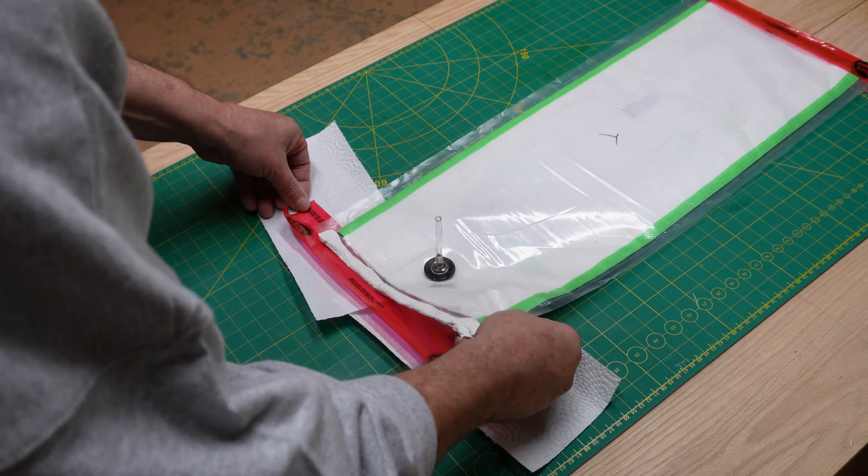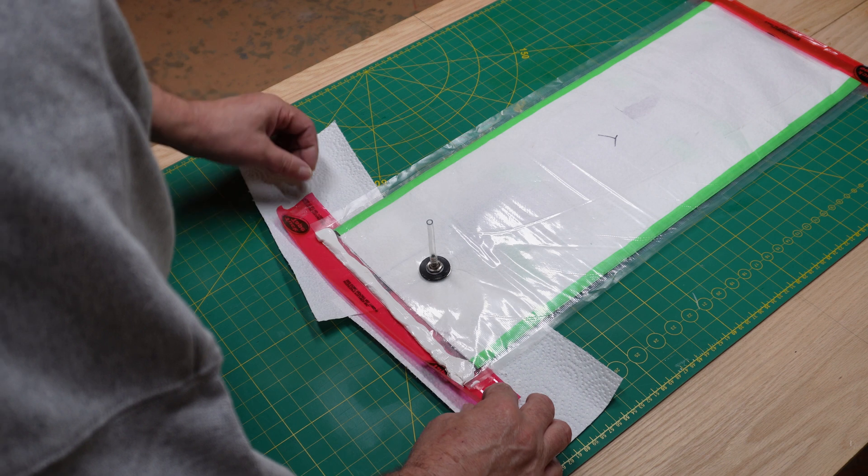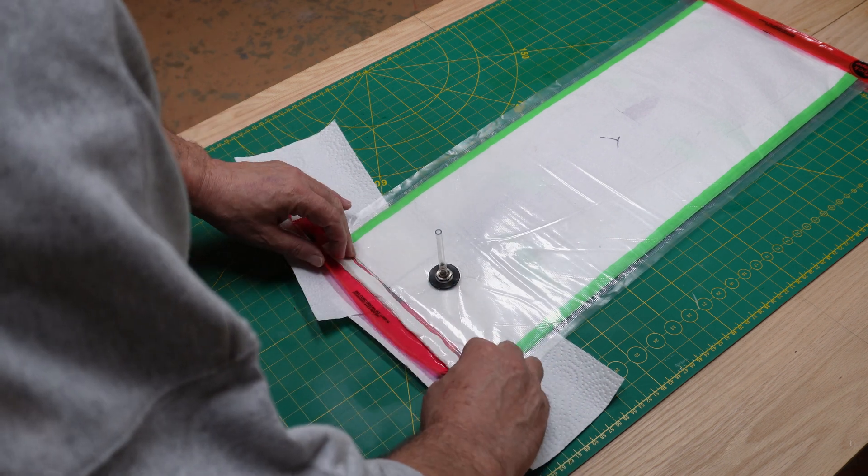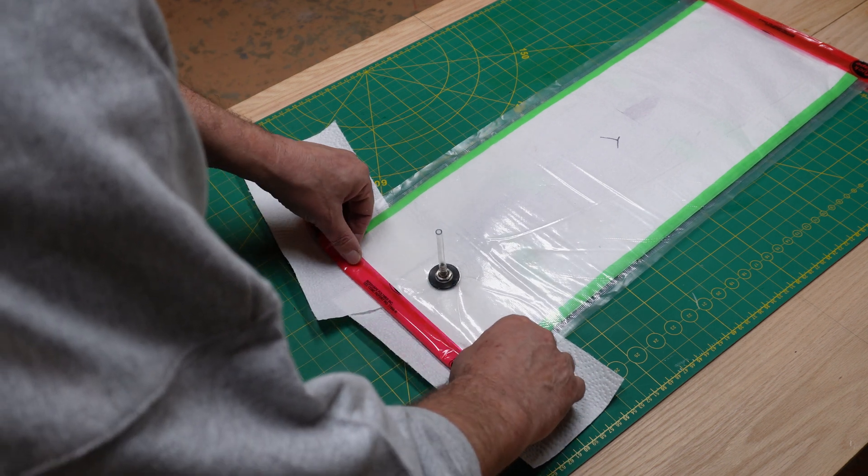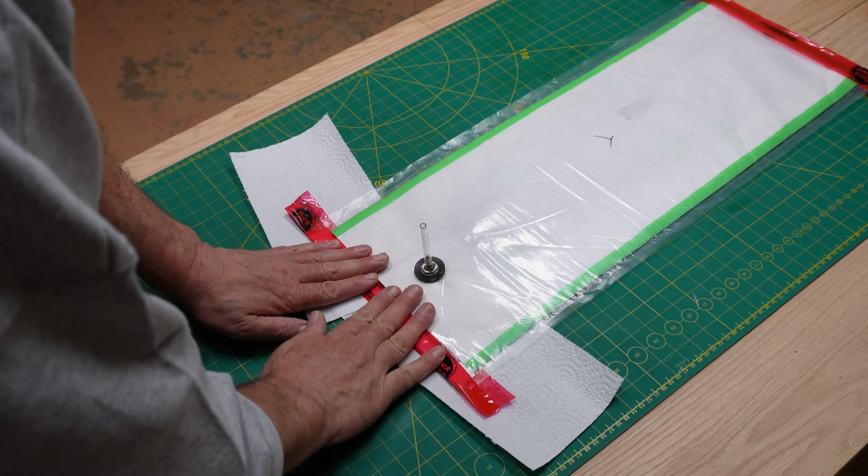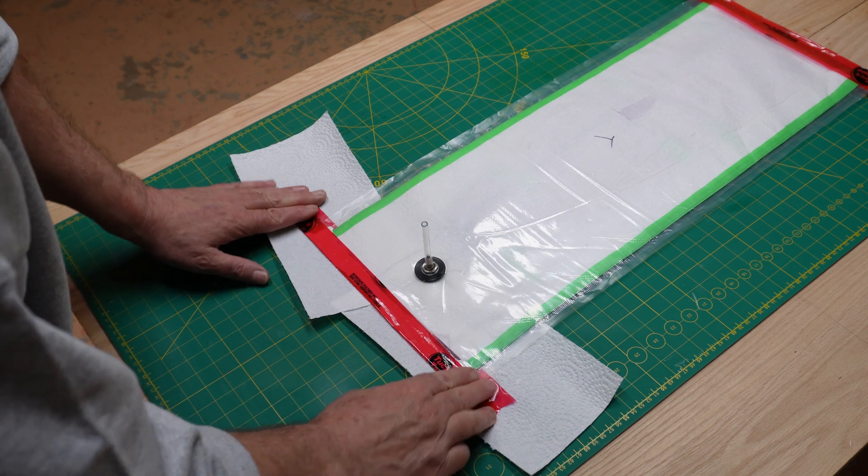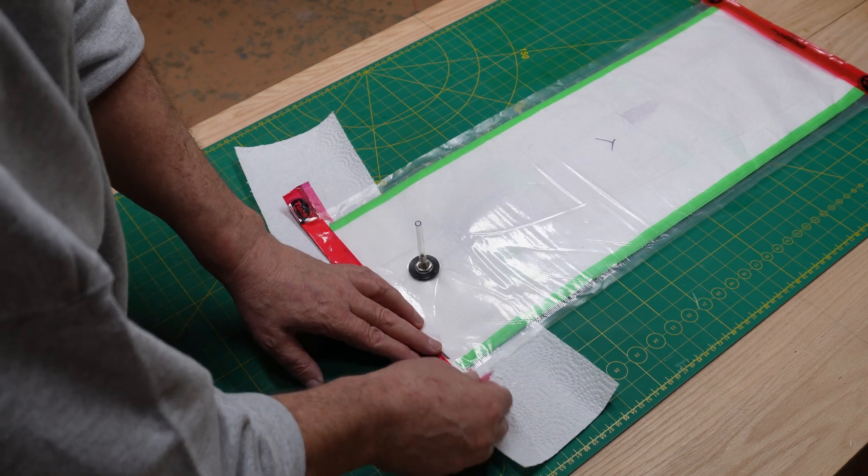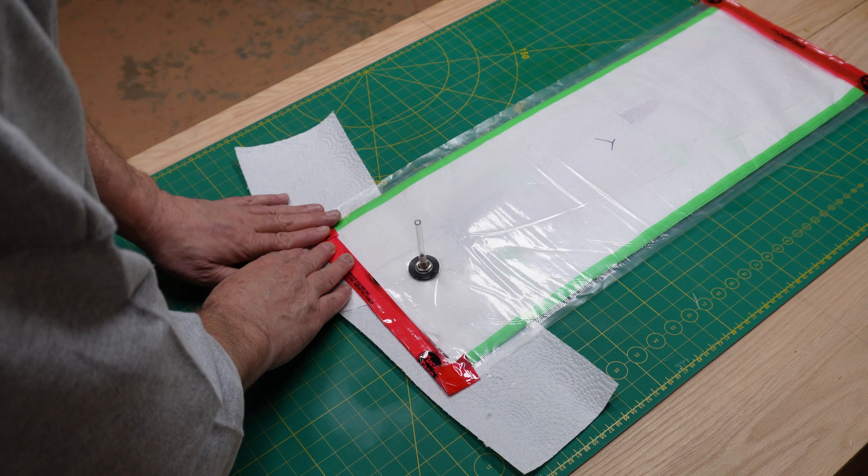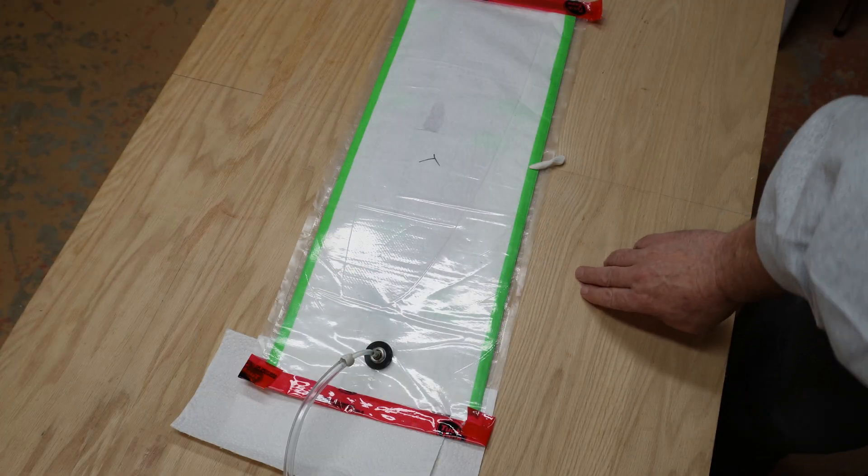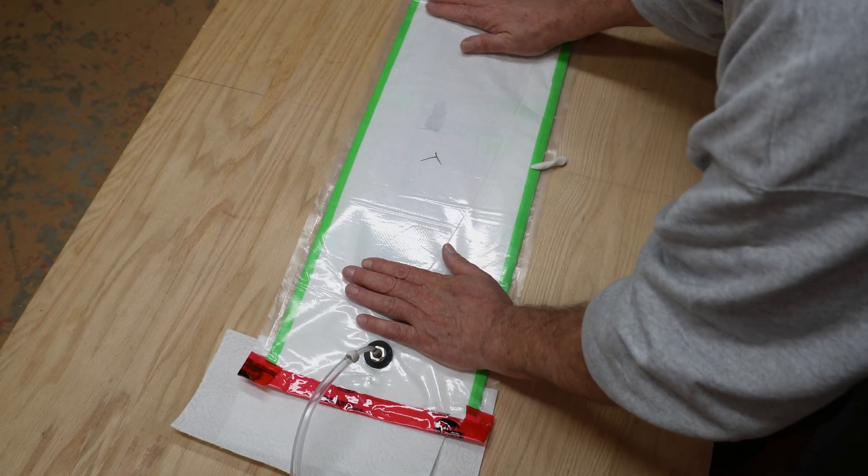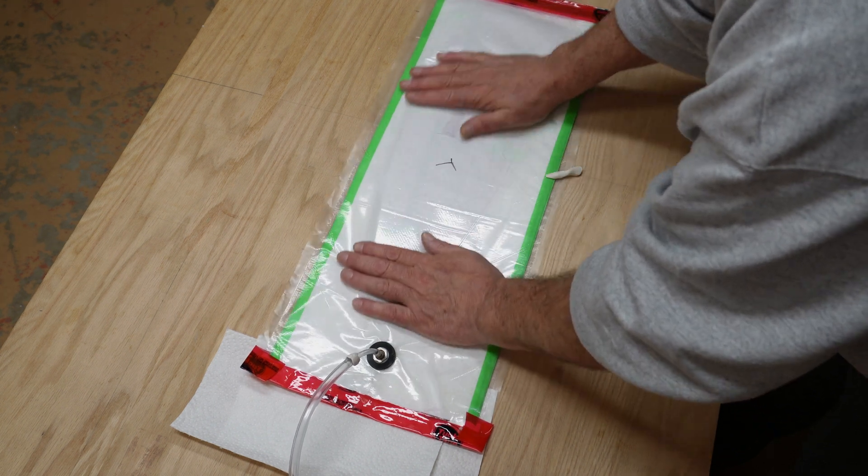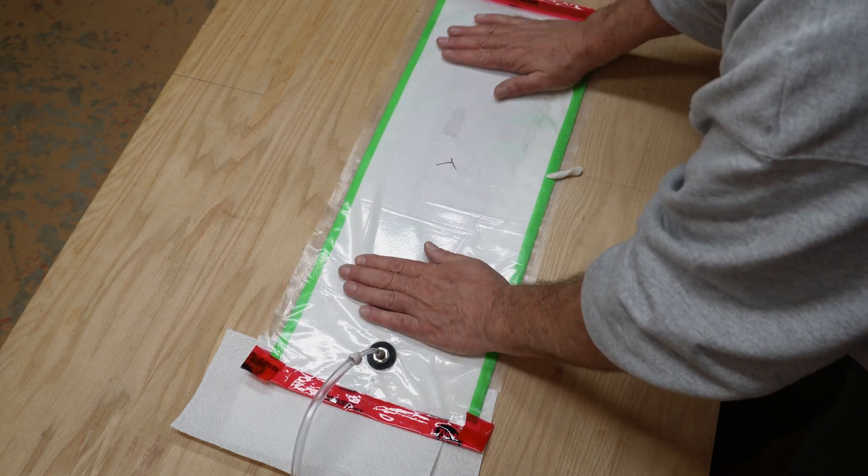I'm gonna put that on there too. Just put that right on top there. I'm going to fold this over the end of the bag and squish that caulking in between it, then fold up the ends between that. Once the vacuum is applied, there is no way that thing's gonna leak. The only leakage I get is from that vacuum fitting most of the time, and I usually take care of that with some modeler's clay.